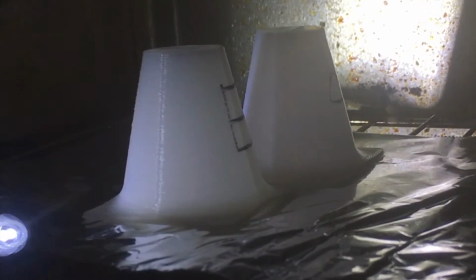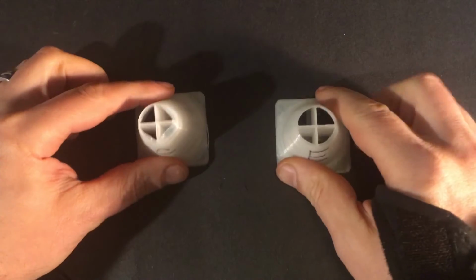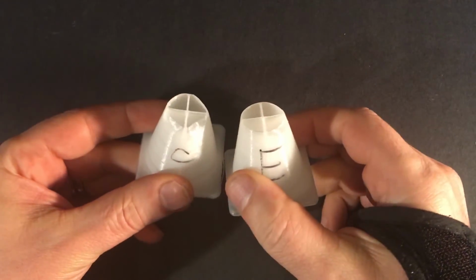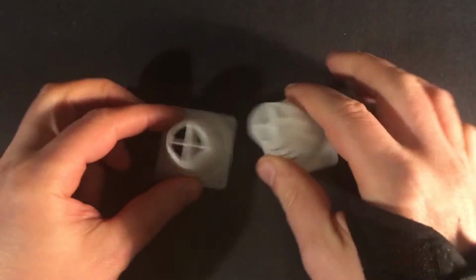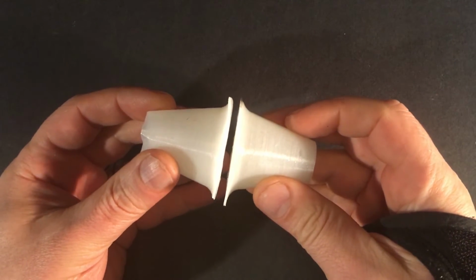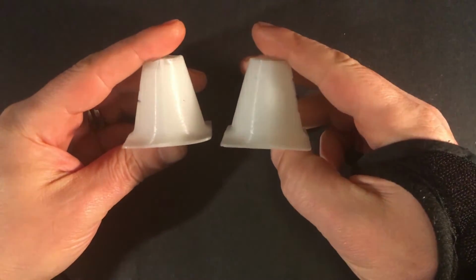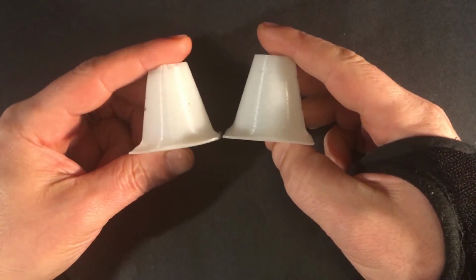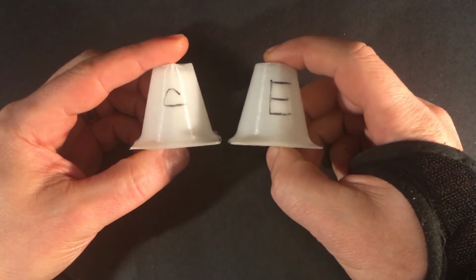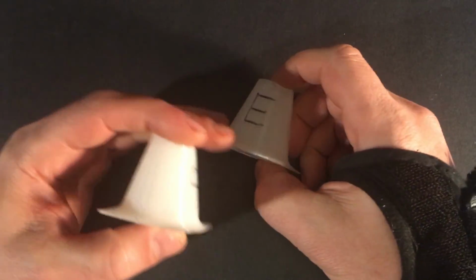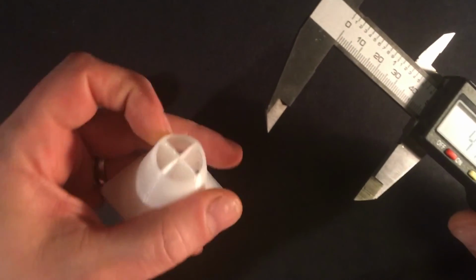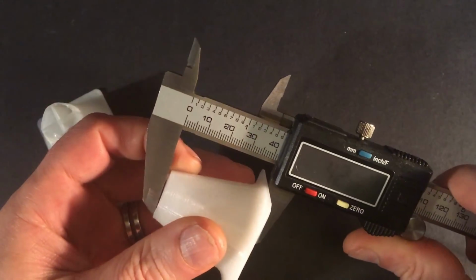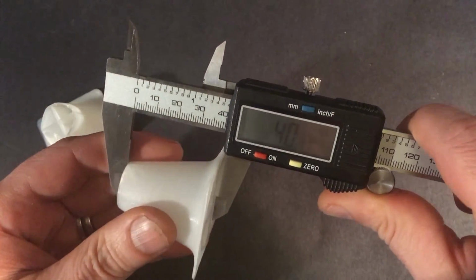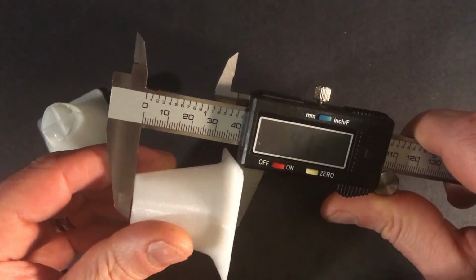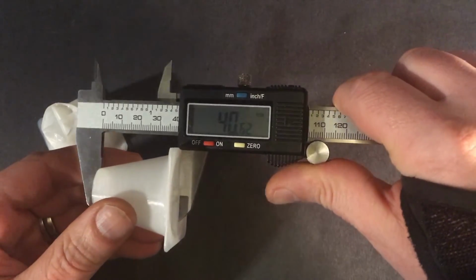So after I heated these up, I can sit them side by side and see the difference between the control on the left and the alcohol treated on the right, the Everclear treated. Very obviously, there's a lot of distortion on the nozzle. You can see on the control, there's a whole bunch of curling on the bottom where there is none on the alcohol treated part. And then if we take a set of cheap calipers and check the dimensions for the alcohol treated part for this 40 millimeter print, we're pretty much still spot on where we were.